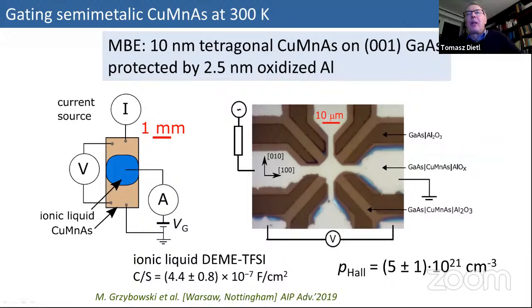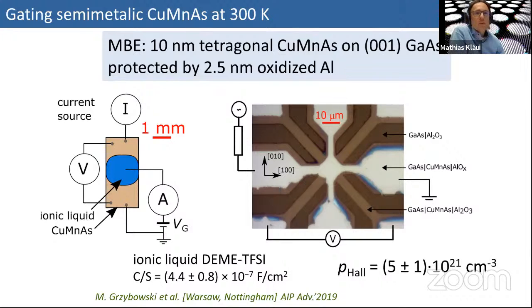We hope not, that we oxidized it properly, but thank you. We have maybe checked more carefully. Thank you for this remark. We thought that we did this properly, but after your remarks we have maybe checked that the oxidation was not full. Let's say we used silicon just to probe capacitance and to see whether we control the capacitance of the system. We had the impression that on silicon we understand capacitance quite well and we control the system, but maybe we should be more careful. Okay. And would you expect theoretically that copper manganese antimony has a similar effect?